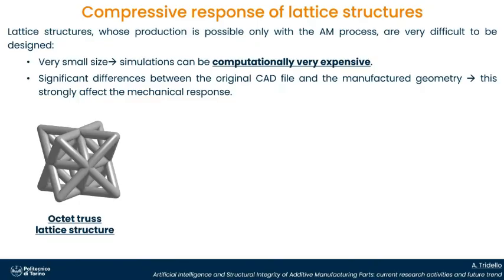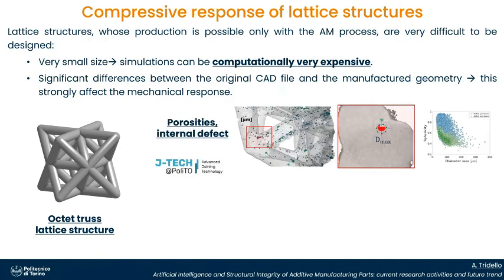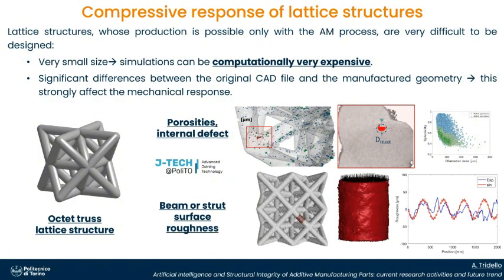We will focus on this octet truss lattice structure. And here you can see the two main defects. One is internal porosity defects; here you can see one taken at the JTech Center in Politecnico. And here you can see the surface roughness of the beam, which has an influence on the compressive response if we want to absorb energy.